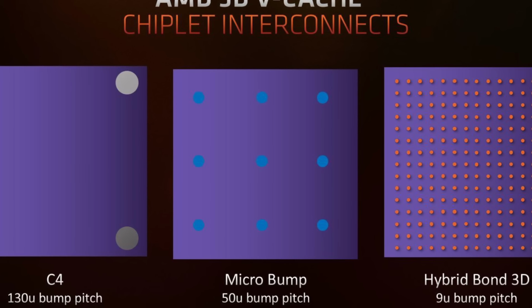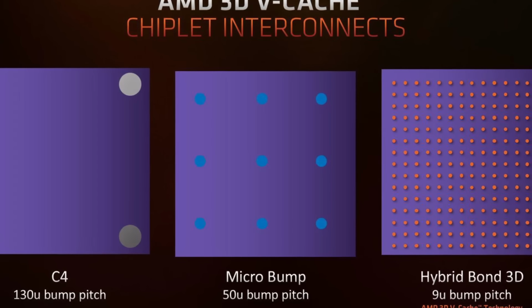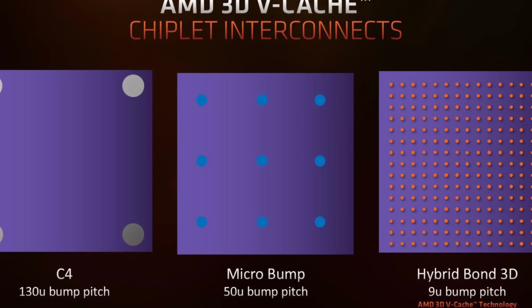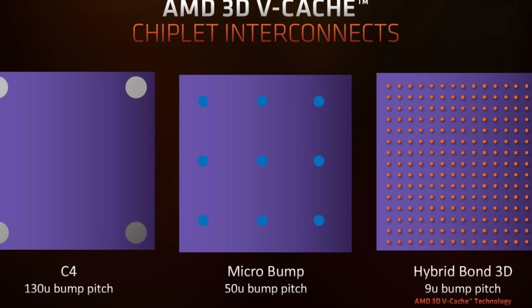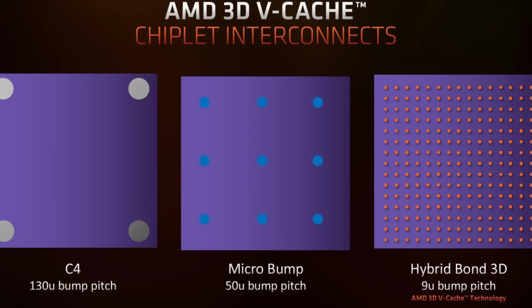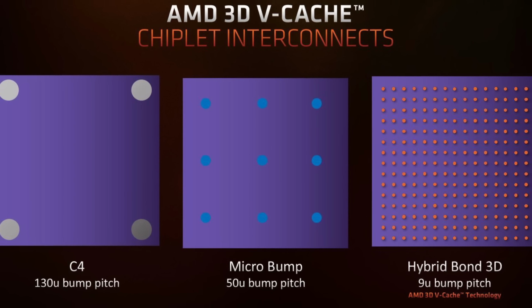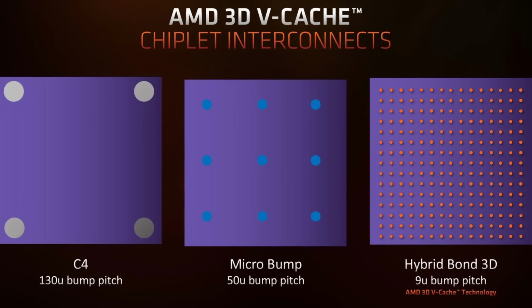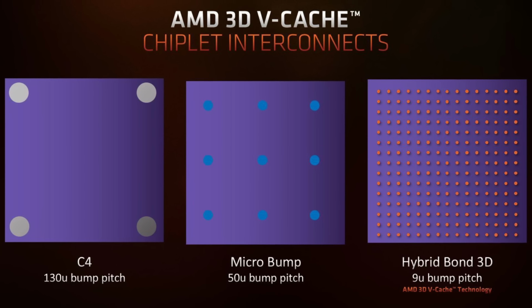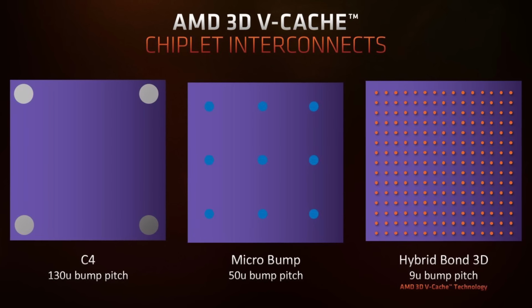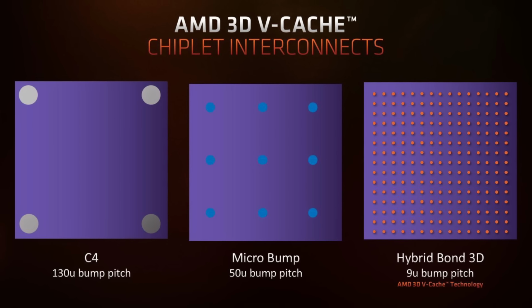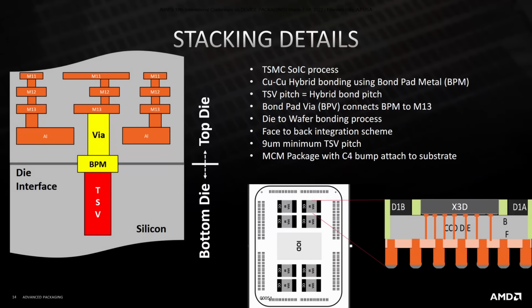This slide gives a very good idea of just how much smaller hybrid bonding interconnects really are. In the image you can see traditional C4 bumps as gray circles and how close they are usually placed to each other. The smaller blue dots are microbumps, a more advanced form but still solder-based, and the orange dots represent hybrid bonding, a massive difference. This means you can bond two chips in a way that they behave almost like one single chip.